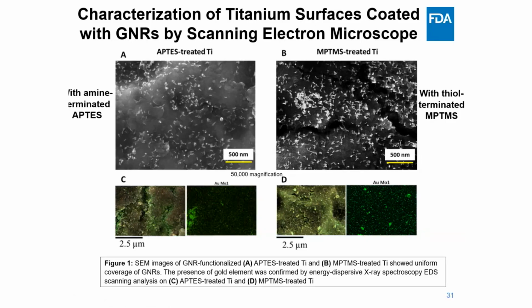Here I'm showing data for characterization of titanium surfaces coated with these gold nanorods from both schemes by scanning electron microscope and elemental energy dispersive X-ray spectroscopy, or EDX, for understanding the elemental map. You can see the first panel is the scanning electron microscope data, whereas the bottom panel shows the EDS elemental maps. You can see that the gold nanorods are successfully attached on both APTES and